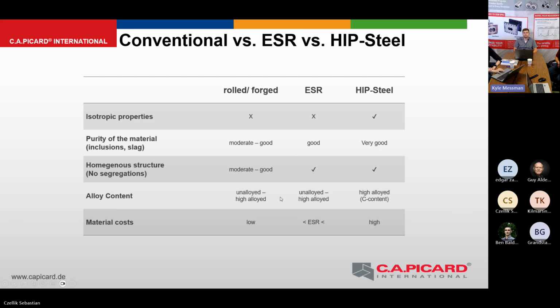Very special about HIP steels is that you can get especially very high carbon content, but also other alloying elements can get higher than they could in a conventional steel. We have steels with a carbon content up to 2.8% and chromium content about 25%. That's really high. But it's a cost point. As you have seen, the HIP process is very long, and you have to do more things than in a conventional process. So the material costs are higher than the rolled and forged steel.